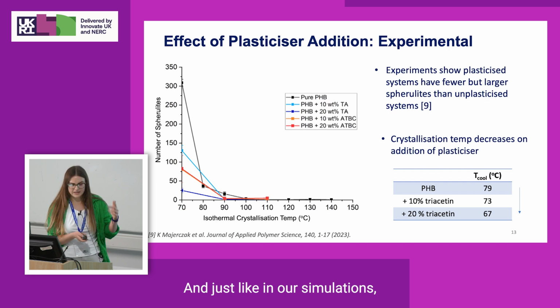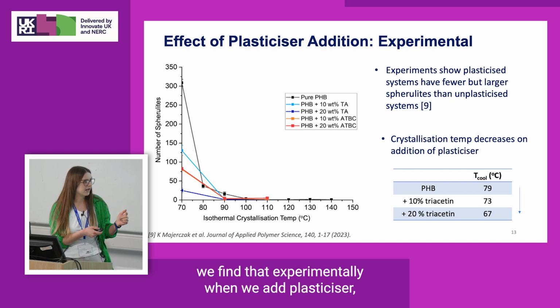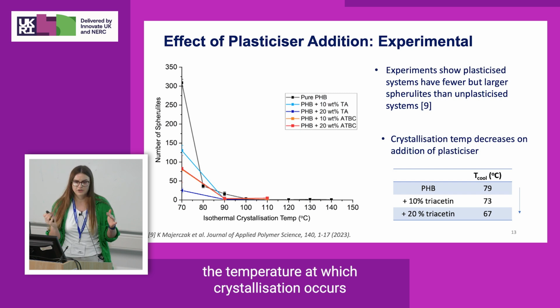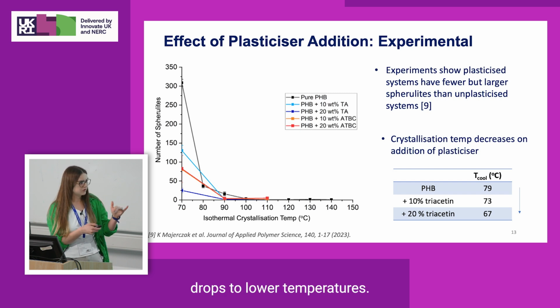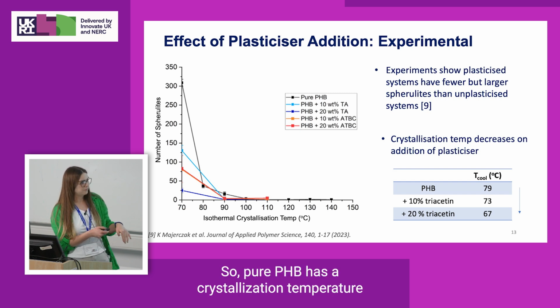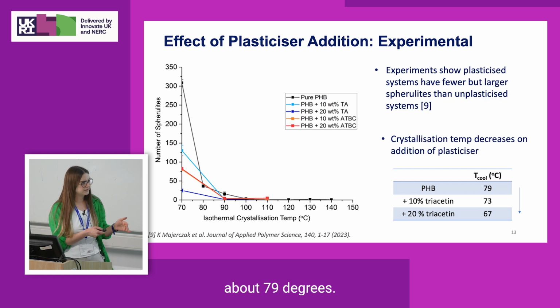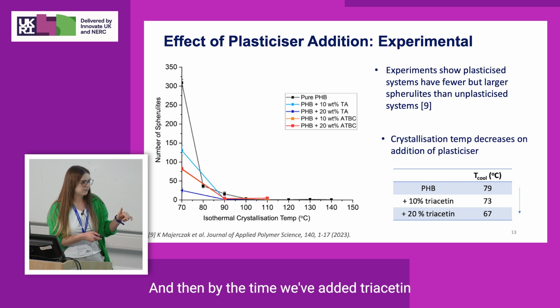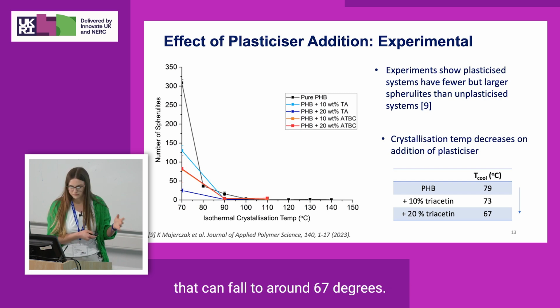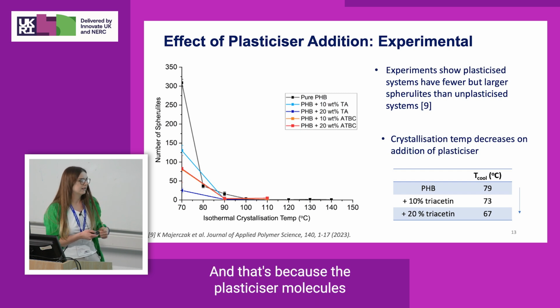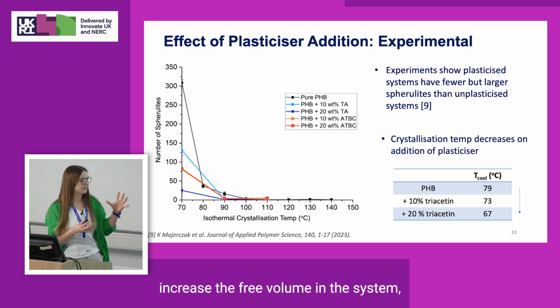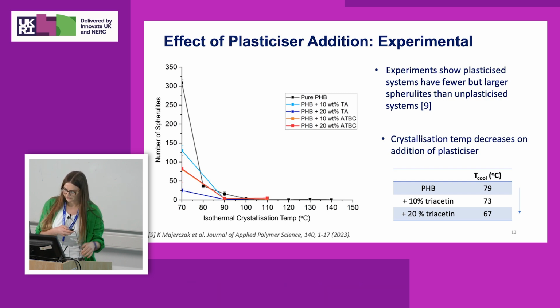And just like in our simulations, we find that experimentally, when we add plasticizer, the temperature at which crystallization occurs drops to lower temperatures. So pure PHB has a crystallization temperature of about 79 degrees, and then by the time we've added triacetin, that can fall to around 67 degrees. And that's because the plasticizer molecules increase the free volume in the system, and more flexible chains need lower temperatures to crystallize.